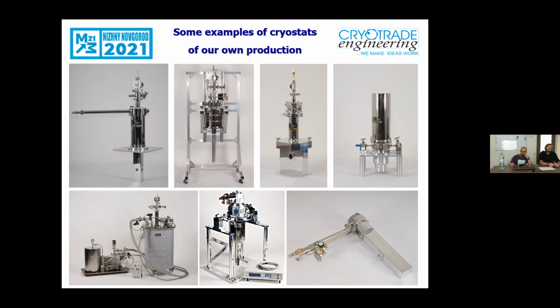The second last cryostat is a very interesting system, very difficult, and was challenging for us. It's a closed cycle system with a 10 Tesla magnet. It was a challenge to build 10 Tesla because it's a combination of two superconducting wires, niobium titanium and niobium tin. It was very tricky to make this magnet, and it's integrated with an exchange gas sample tube, which is cooled down with a third loop of helium.